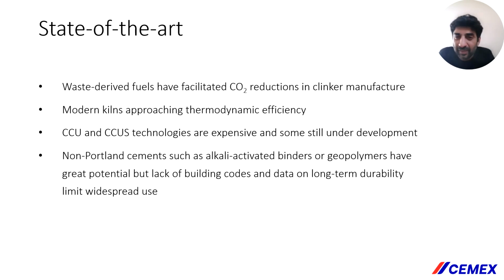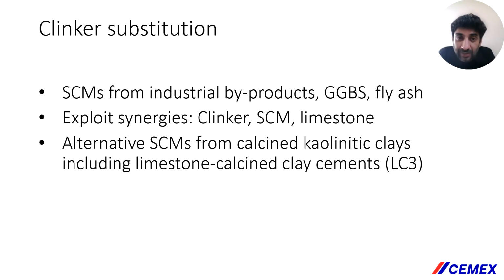Non-Portland cements such as alkali activated binders or geopolymers have immense potential, but lack of building codes and data on long-term durability limit widespread use. Clinker substitution with SCMs from industrial byproducts, in particular GGBS and fly ash, is still a widely used and effective approach to cut carbon emissions by 30 to 40% without considerable changes in strength, durability, and costs. The main issue, as we know, is that both slag and fly ash are only available in rather limited quantities.